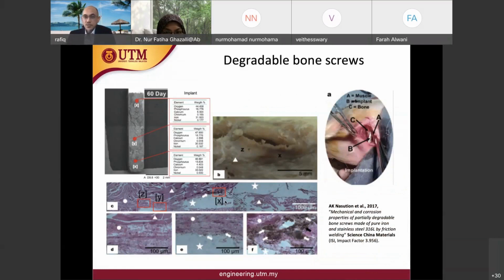Right, as I mentioned, we tried and are still working on functionally graded biomaterial, FGBM, and this one is one of the successful works that we have done related to FGBM, pure iron with stainless steel. So we have two parts. That's the pin. The pin consists of two different materials: pure iron on top, and stainless steel 316L at the bottom. The way we fuse these two materials is through friction welding, which involves a very high temperature.